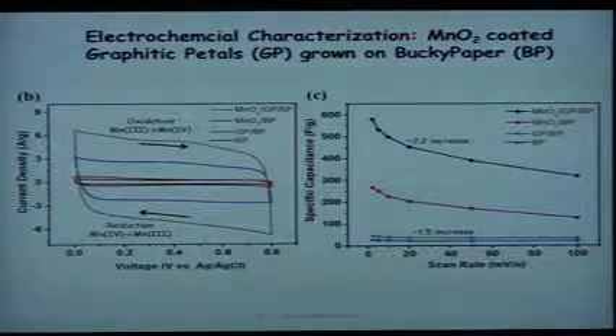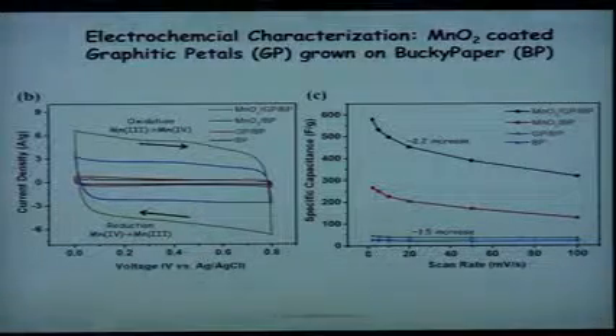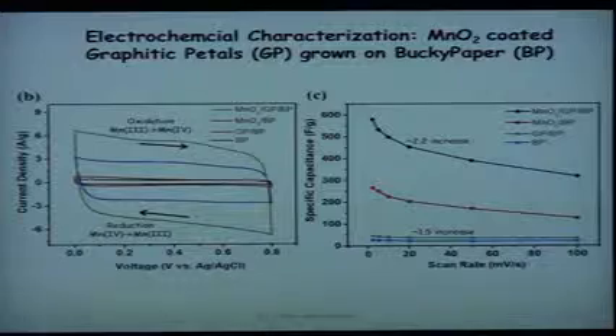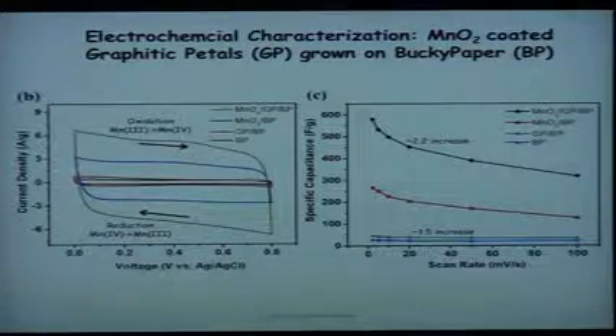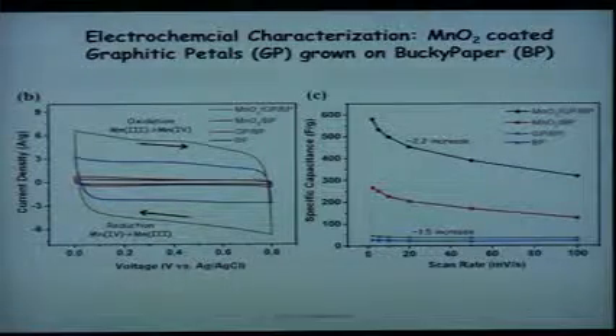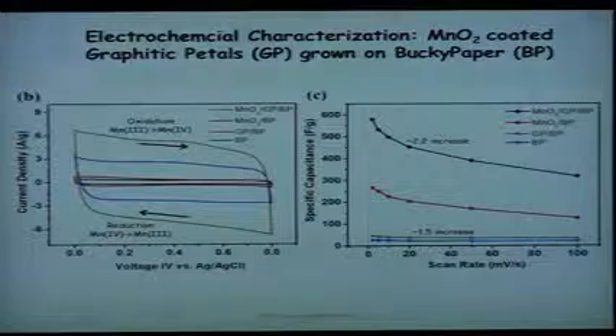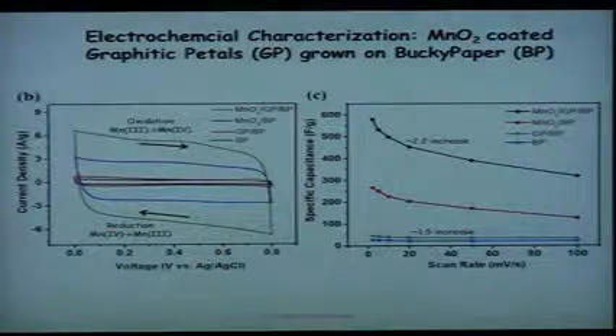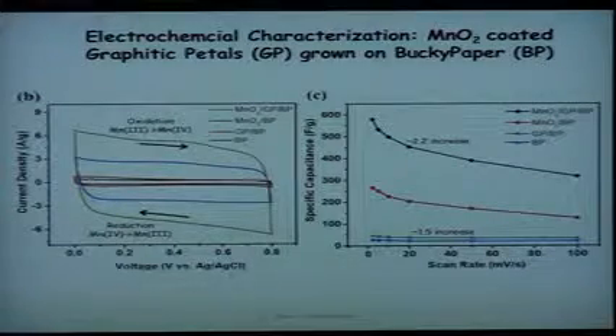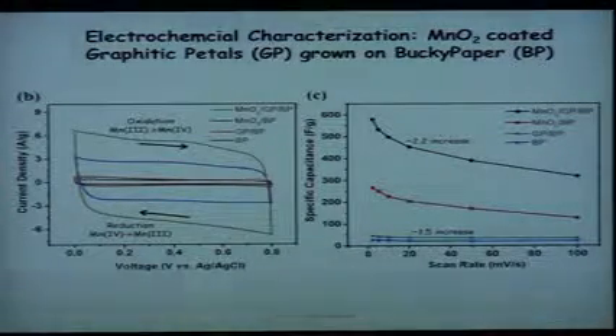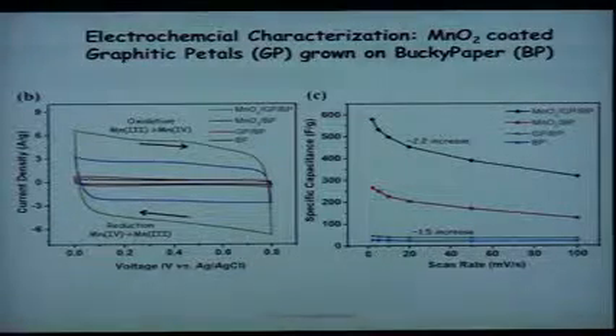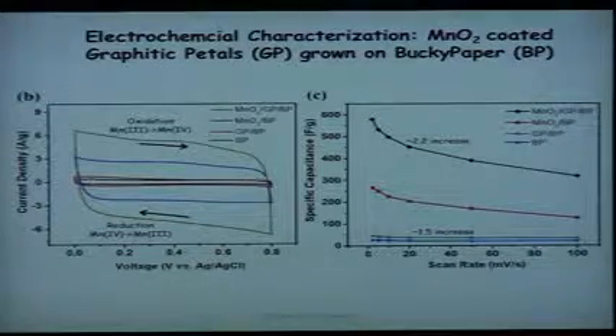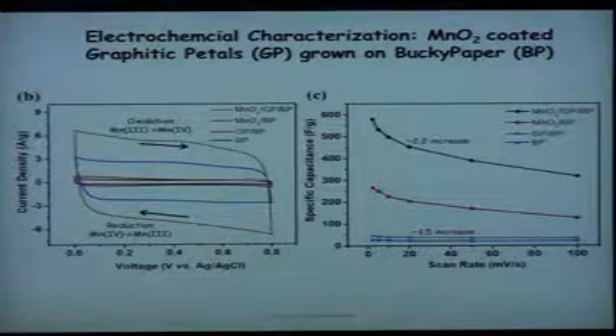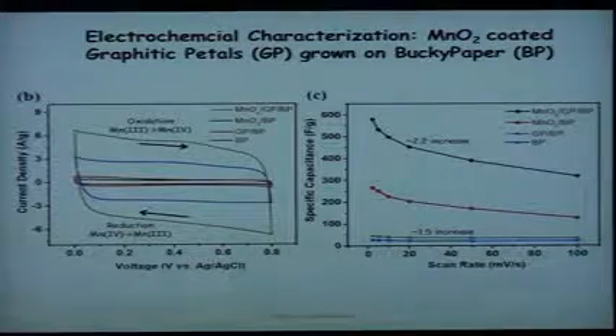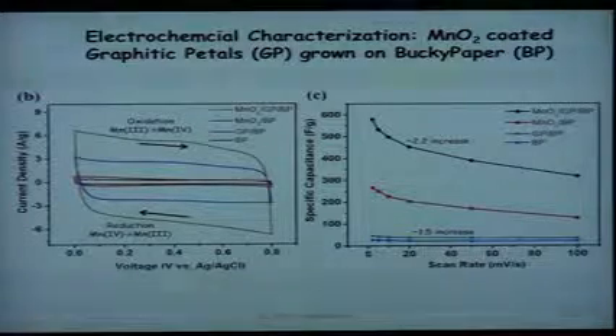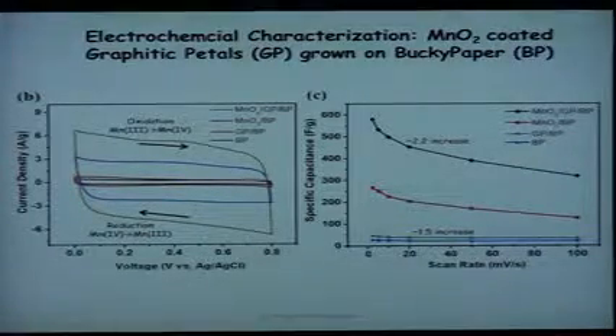So here's the CV curve. It looks pretty good, not quite rectangular. The bottom ones are pretty well rectangular. In this case, we're showing you the different stages of growth. So if we just have BuckyPaper with that electrolyte, you get this double layer capacitance, but it's really small. When we add petals to the BuckyPaper, again in that electrolyte, so that would be like a double layer capacitor, we get the red curve. When we have manganese oxide on BuckyPaper alone, we get the blue curve. And then when we have everything together, BuckyPaper, petals, manganese oxide, we get the top curve. So this is not different scan rates. This is showing the effect of the materials.